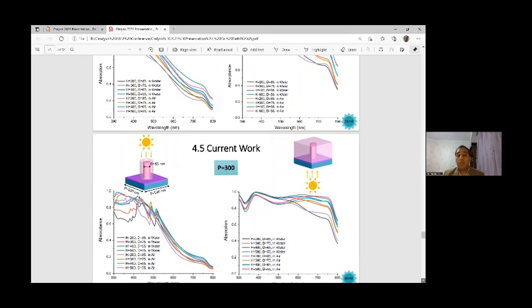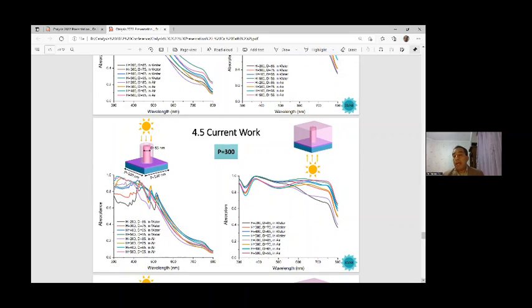But for structure 3, the best case is obtained for P equal to 400 nanometers. This is because for structure 3, we have placed more perovskite material. This enhancement of performance is related to more perovskite material around the nanorod TiO2 structure, and this result is due to the behavior of perovskite, which we focus on as an important structure and element in my lecture and presentation.